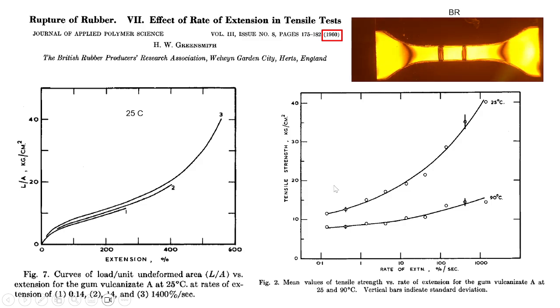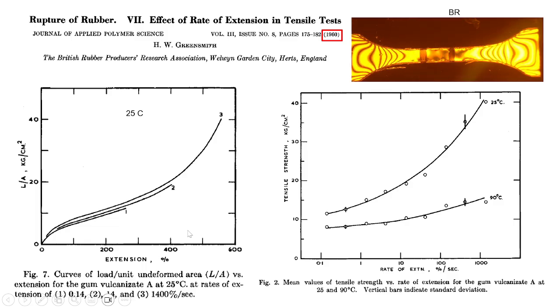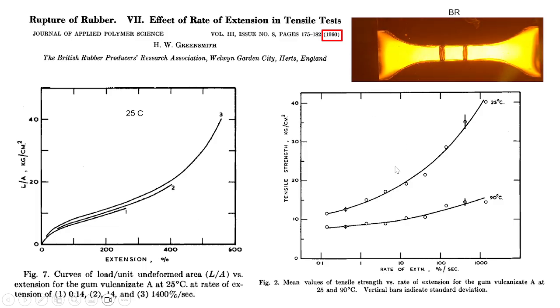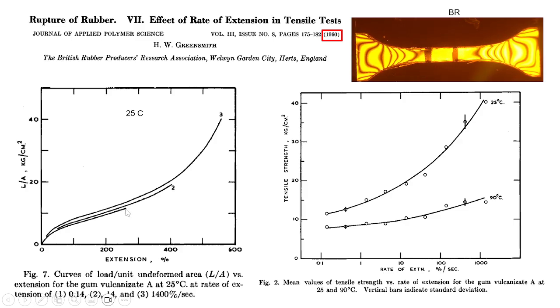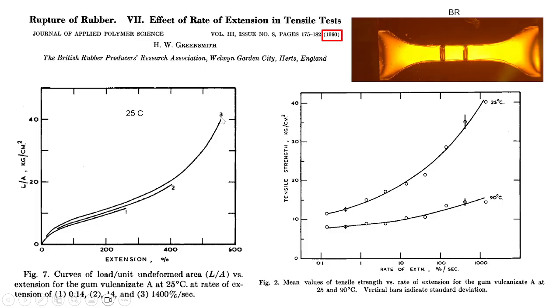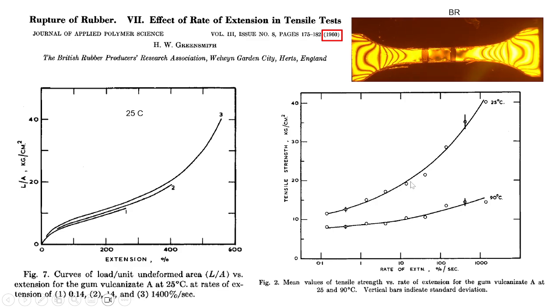So here's the actual data. I was just verbalizing what I told you. So you can imagine a so-called rupture problem. It was known since the 1960s that if you use a low rate, it will rupture here, a higher rate ruptures here, an even higher rate ruptures there. If you plot these 3 points as a function of the rate, you get this line. The higher the rate, the stronger it is.